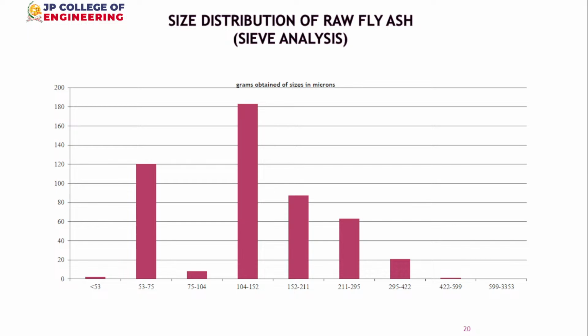but having even some 500 micron particles. 500 micron is 0.5 millimeter. Some are larger particles. There are some submicron particles also available, but they're very low in amount. So this ash could not be used for our purpose, because it will not improve our mechanical properties. It will deteriorate the mechanical property, this kind of coarse particle addition.